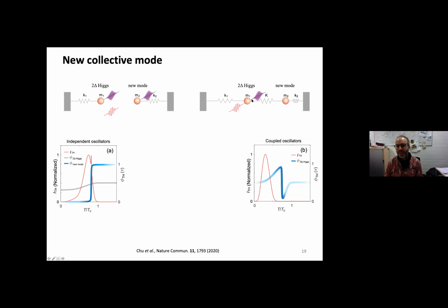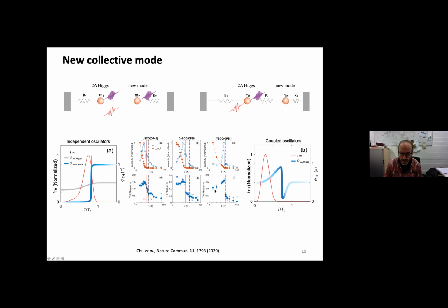However, if we would take a coupled oscillator model and would model something like this, then we would really get a phase jump from high to low about the anti-resonance condition of these two coupled oscillators. And that is an observation that is very, very close to what we find in our experiments.